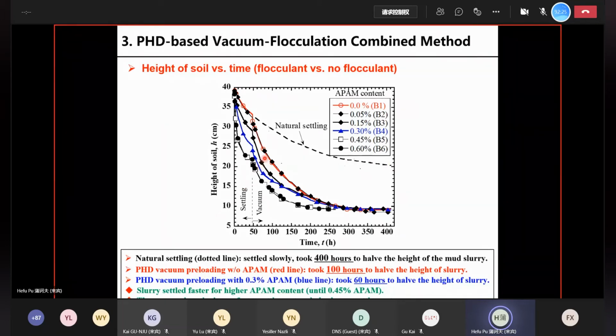In contrast, if you look at the red curve, in this case we added in the vacuum pressure. The dewatering process is significantly increased. You can see that it took only about 100 hours here to reach 50% deformation. And on top of that, if we further add in the flocculant, we can see that the dewatering process is further increased. In general, the slurry settled faster for increasing APAM content. So overall, the proposed method gave faster settlement, but also larger magnitude of settlement.